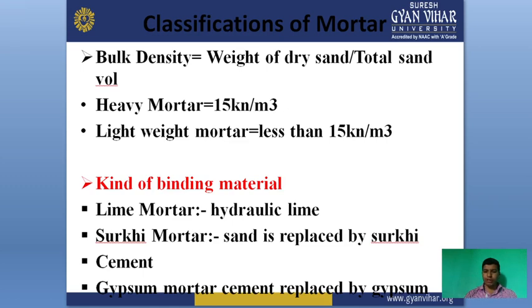In the pounding method, lime and sand are mixed in a dry state, the mixture is placed into pits, and then water is added to the mixture while it is repeatedly turned up and down.